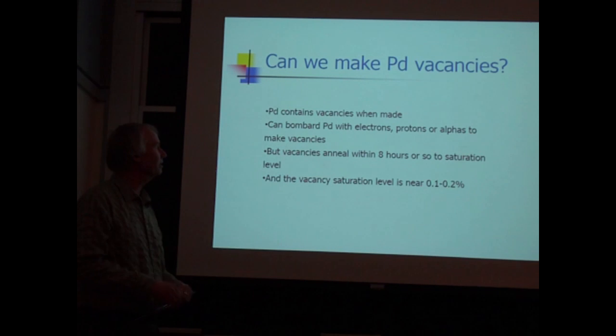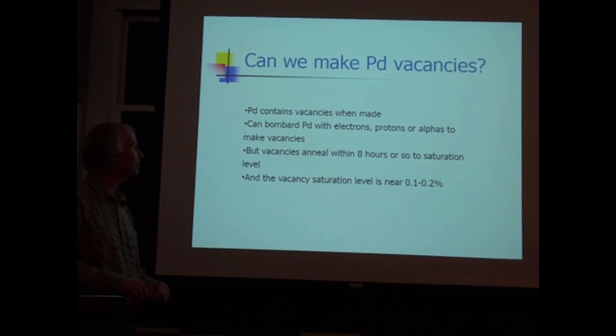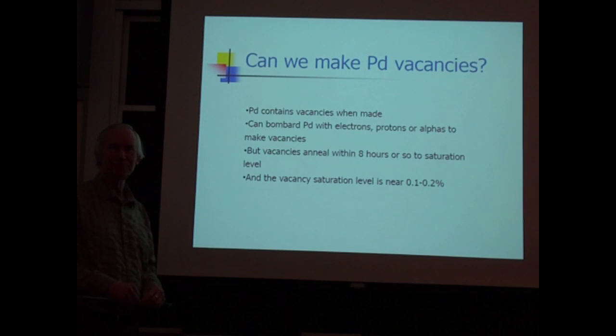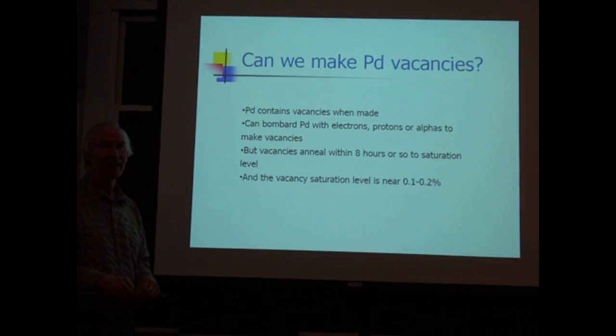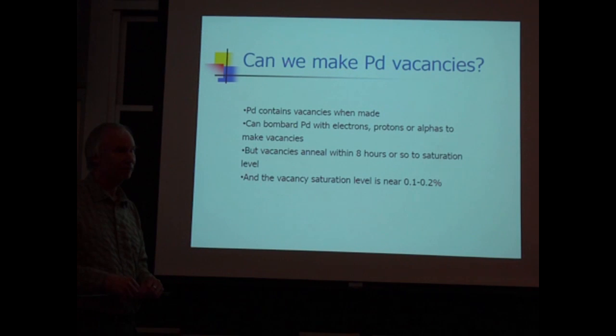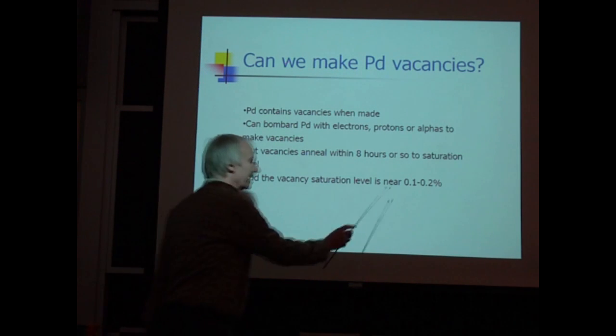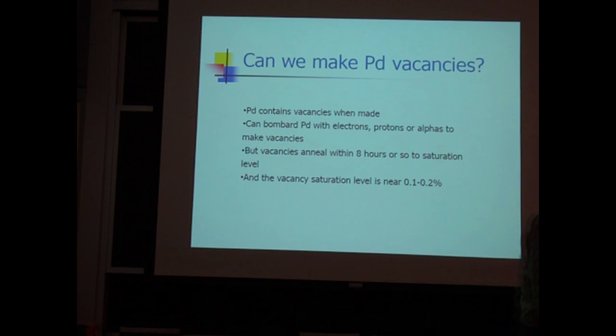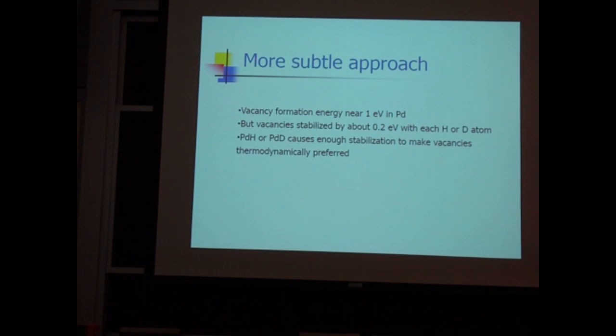In the case that we did, we bombarded palladium and nickel with electrons, made a lot of vacancies, and watched them go away. They anneal. If you make a lot of vacancies with electron beam bombardment, at least in the case of palladium, they anneal back to the saturation density, which is between 0.1 and 0.2%. In metallurgy, that's a huge number of vacancies. From my perspective, from the cold fusion business, that's nowhere near enough vacancies even to begin to be interested in. So saturation fraction of vacancies, from my perspective, is not interesting.